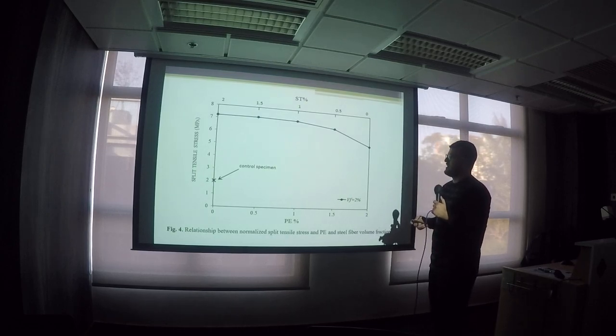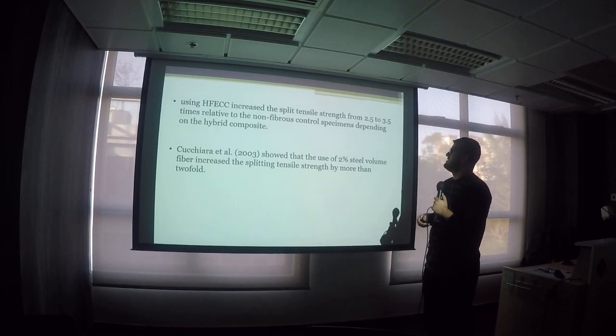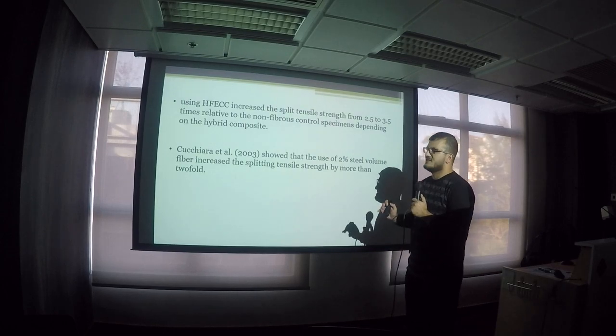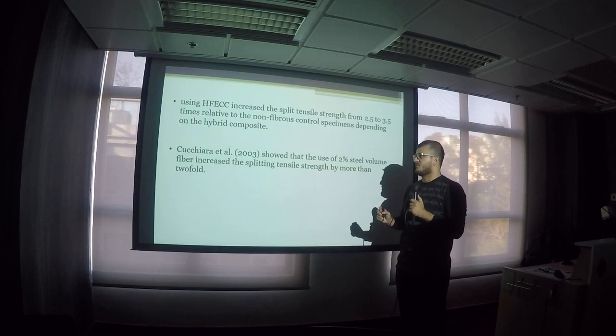Also, another relationship is plotted here in figure 4, which is the relationship between the split tensile strength and the hybridization ratio. As you can see here, increasing the steel fiber in the composite slightly increased the split tensile strength. However, once we reach 1% of steel fiber, no extra enhancement was noticed after increasing the steel fiber above 1%. And if you compare the hybrid fibers to the control specimens, which are non-fibrous, we can see that the split tensile strength has increased between 2.5 and 3.5 times relative to the non-fibrous material.